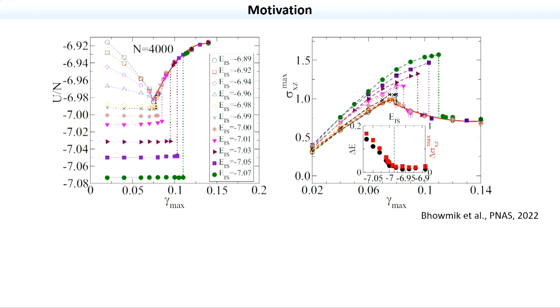And now interestingly, if you start with a high potential energy state, let's say the system is poorly annealed, then you can apply a cyclic shear strain of amplitude, this gamma max, and you vary that amplitude. So you see that the potential energy goes to lower and lower value before the material yields, then again as a function of strain, it goes up again. So for a certain range of strain amplitude, the poorly annealed initial state can be made better annealed. But for these curves which are already annealed, not by shear, but by some temperature preconditioning to reduce this energy very much, the shear doesn't have much effect. See, it remains flat, and at some point it abruptly yields.